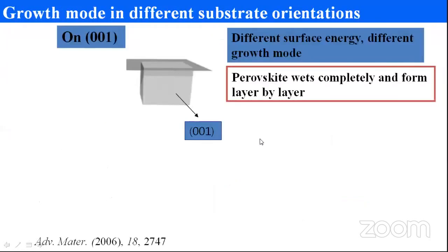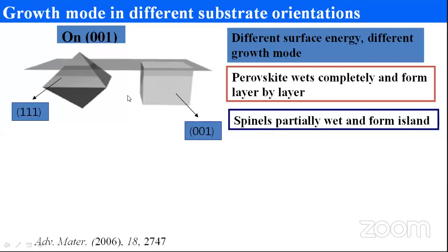Okay, what will happen if you put one more material, a perovskite material, on that? Perovskite, as I said in the beginning, is a cubic structure, so this is a 001 structure on a 001 substrate. This perovskite wets the substrate completely and grows layer by layer, and the 111 phase spinels partially wet and grow as islands. So if you put both together, your perovskite will grow layer by layer, and your spinel will grow as islands.